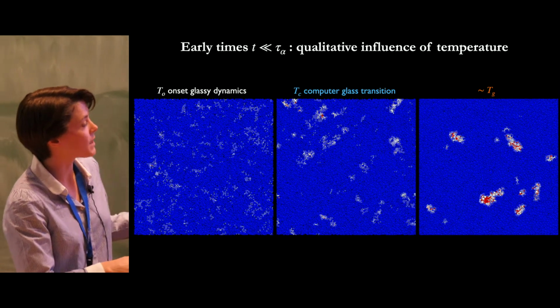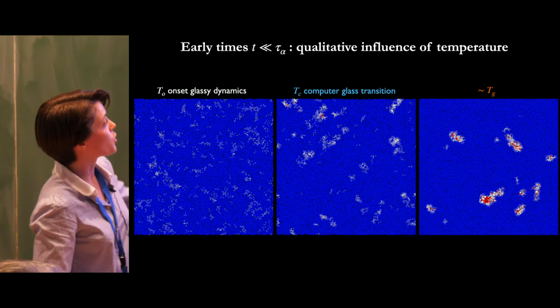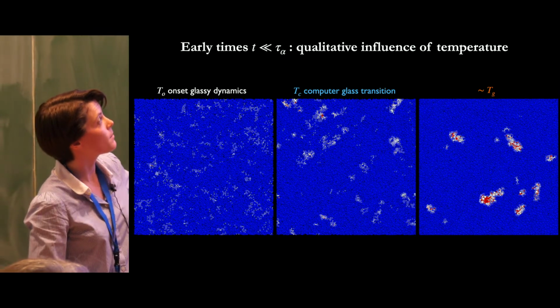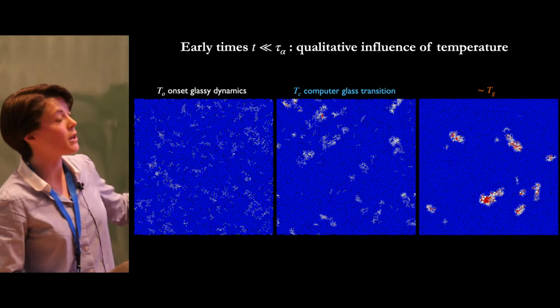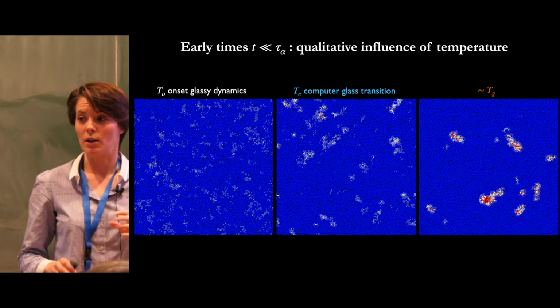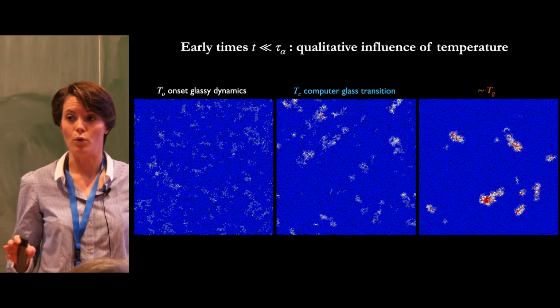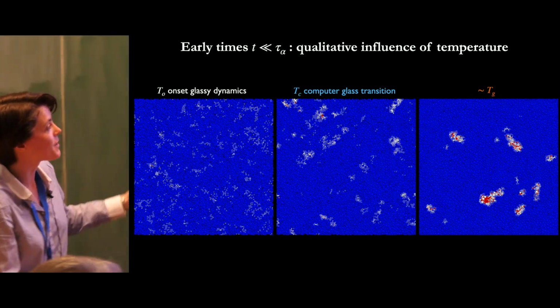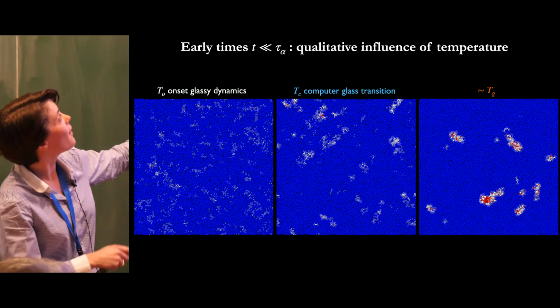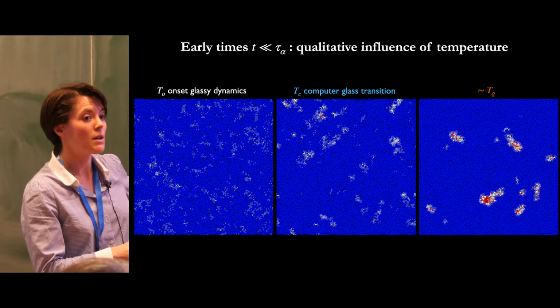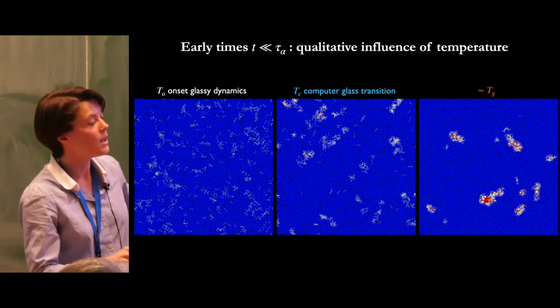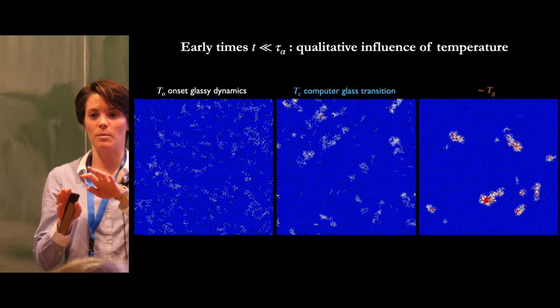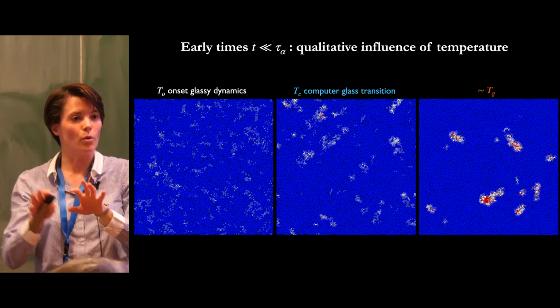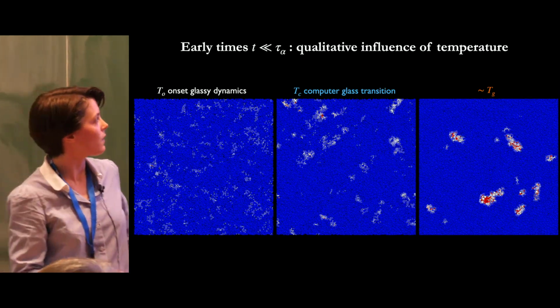But if we go to slightly higher temperatures, here I'm showing typical snapshots of the system when the decorrelation is around the same. So let's say 2% of the particles have moved. What you see here, actually not so well, but that's probably the main point: at the onset of the glassy dynamics, you have particles that are a bit whitish, meaning that they lost maybe one neighbor. So the motion is really highly collective and quite soft.